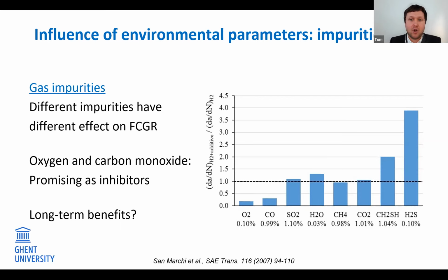This is shown in the graph here, where the effect of impurities on the fatigue crack growth behavior of a low alloy steel is shown, relative to the behavior in pure hydrogen, as you can see on the y-axis. Gases like oxygen and carbon monoxide show a dominant inhibiting effect when in combination with hydrogen, while, for instance, methane and carbon dioxide had only a small effect on the crack propagation when added to hydrogen.